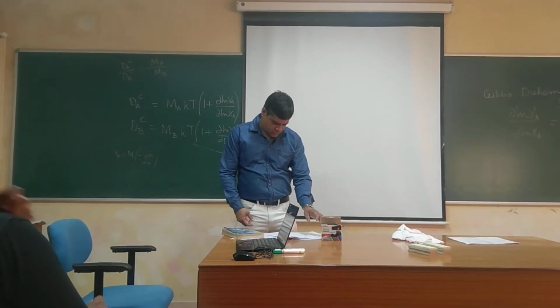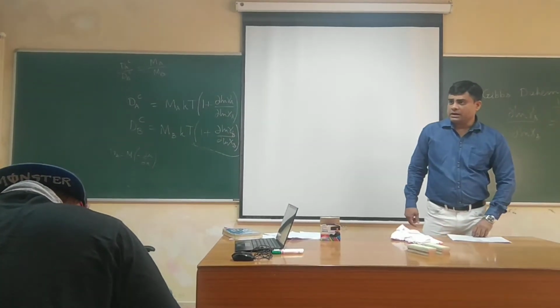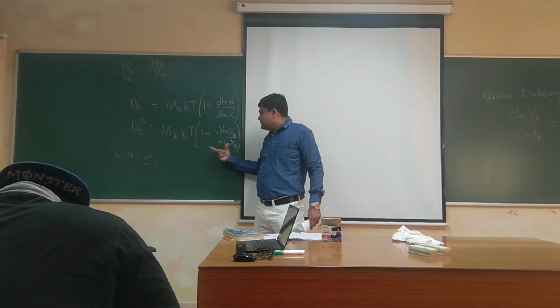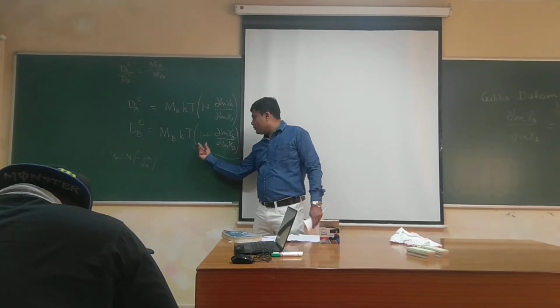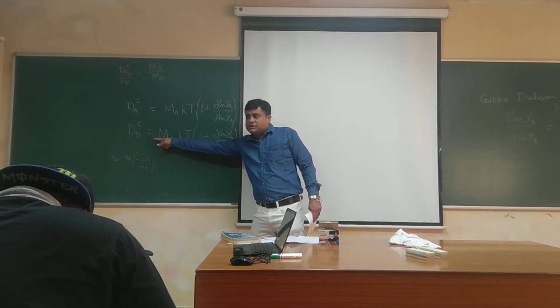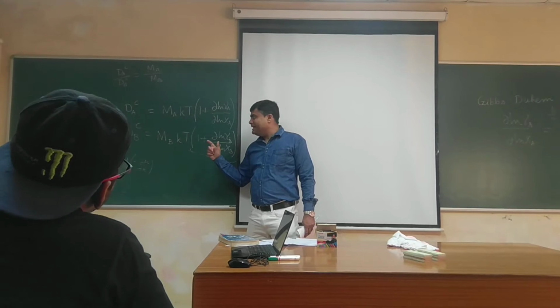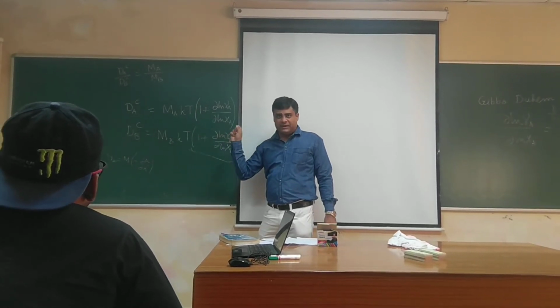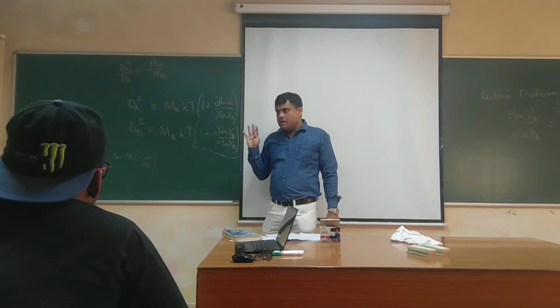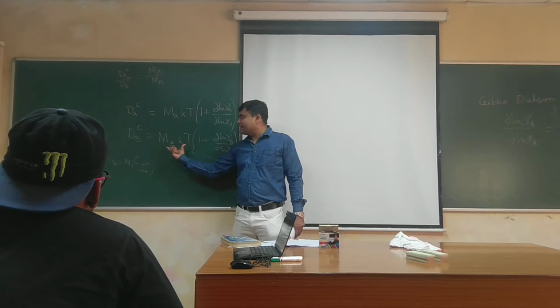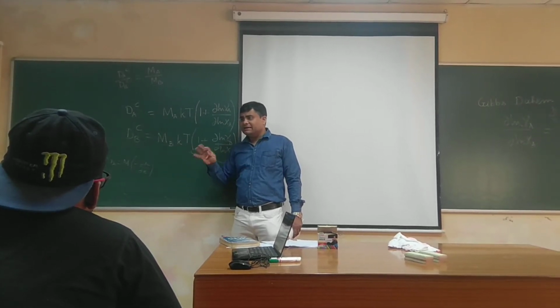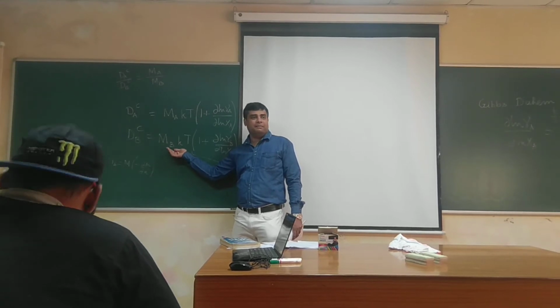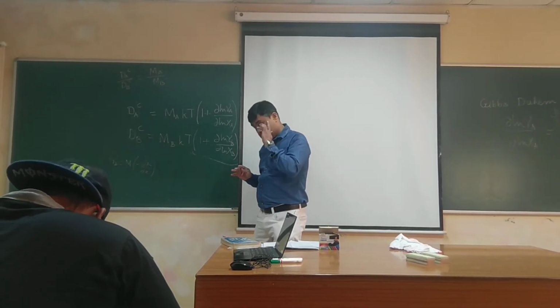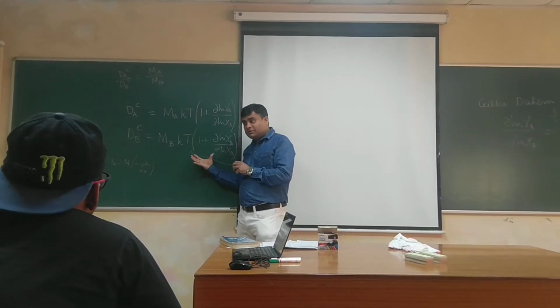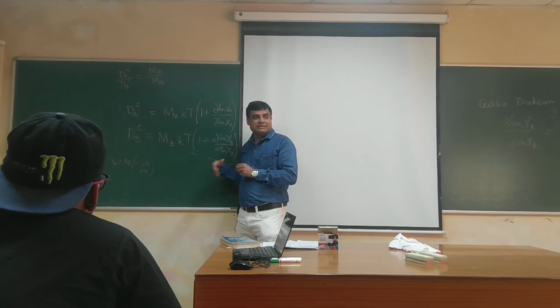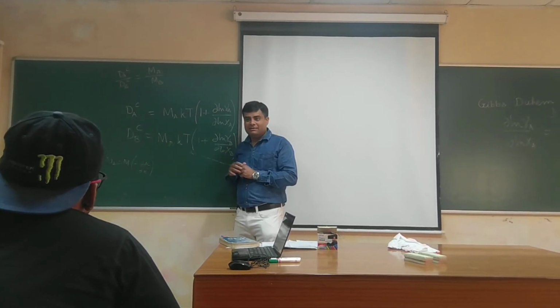Can I repeat this? What I am saying is that for ideal solution, this becomes zero. So 1 plus 0 is 1. So for ideal solution, DB equal to MBkT, or intrinsic diffusion coefficient of any component is mobility multiplied by kT. For non-ideal solution, it is that. In ideal case, it is just the random jump through which the diffusion happens through thermal agitation. And in non-ideal case, this is the added factor that is acting as a weight over and above the